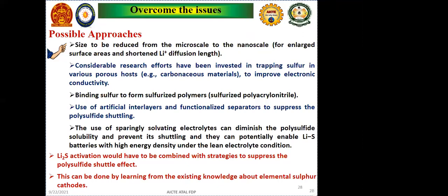Then we can also go for binding the sulfur with some polymers like sulfurized polyacrylonitrile, or some other polymer, or especially we use the electrolyte to bind with the cathode material, so that there will be sufficient electrolyte during the charge discharge, as well as sufficient electrolyte in the system. So what we do, we just add the electrolyte in a proper ratio, where we can also increase the conductivity of the cathode, as well as help the system to have sufficient electrolyte.